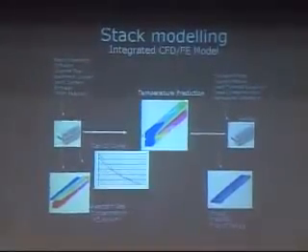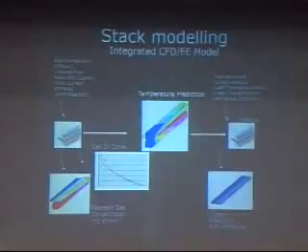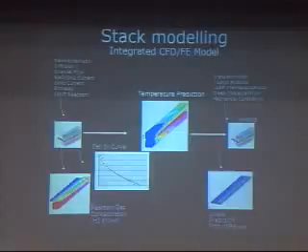But equally, we have to produce the overall structures. And I spoke earlier about the need to design the structures. In this particular fuel cell, the way that the fuel cell is constructed is a very thin stainless steel plate is used as a support, and the electrochemically active elements, the electrode, the electrolyte, the electrode, are placed down onto that sheet using a system very similar to printing. It produces a fuel cell that is just a few microns thick.